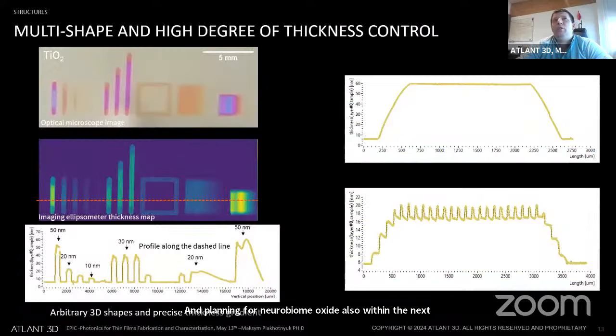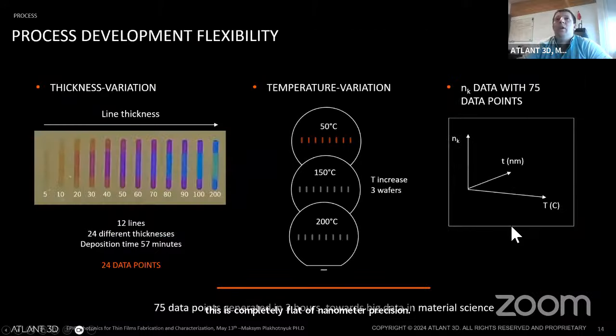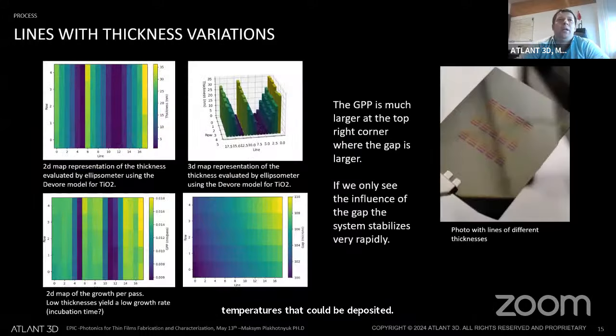What we do with this technology, we have flexibility in the thickness control, geometry control, gradient thickness control, roughness control, so we can easily modulate roughness. As you could see, this is comparison of 2 surfaces which we rastered. So this is completely flat with nanometer precision. This is with structures. We easily do have a flexibility over process development, so variation in the thickness, as you could see, from 5 nanometers, like 200, and the same wafer variation in the different temperatures that could be deposited. And this is one of the examples of these structures deposited on the same element.